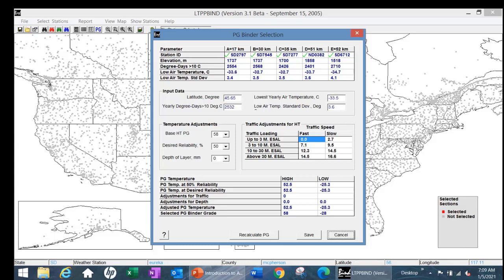So I can go in and, based upon what reliability, high traffic, high volume road versus a low traffic road, and depth in, and the rate of loading, fast versus slow, I can compensate this and come up with a fairly accurate PG binder grade selection. In this particular instance, it was 58 minus 29. You can do this for any place. This is really good if you're a consultant on the DOT design or making recommendations.